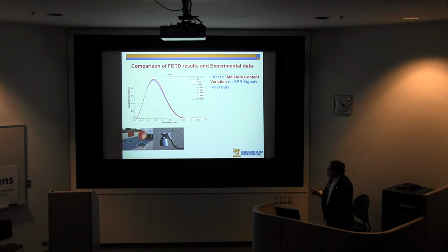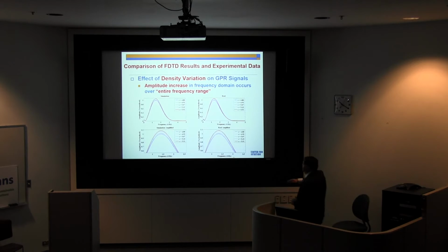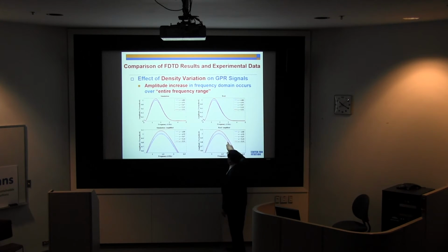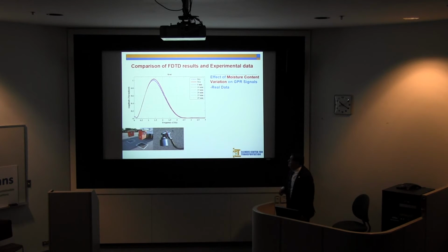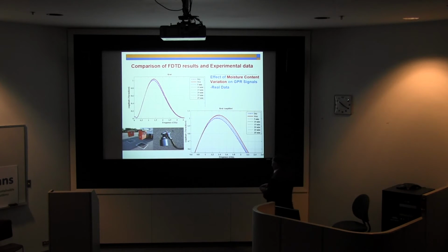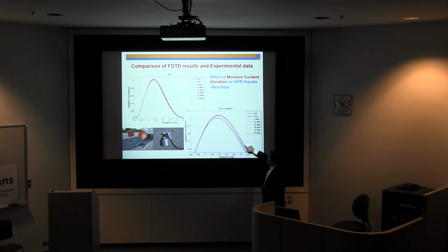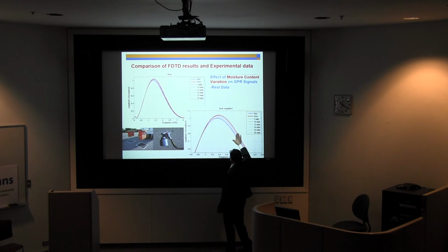What I would like you to do now, when I was putting the water here, you look at the curve, and something will attract your attention. When I change the dielectric constant before, the whole thing is moving, okay? Because of the dielectric constant. But when I put the water in, you can see in the upper range of the frequency, things are moving, but at the lower range of frequency, it's not. And now we're going to be using this for our advantage, okay? So if I get closer up here, you can see this big difference here. This is the dry, okay? This is the wet. And as I let it dry, it starts coming down, but it's all in this area.